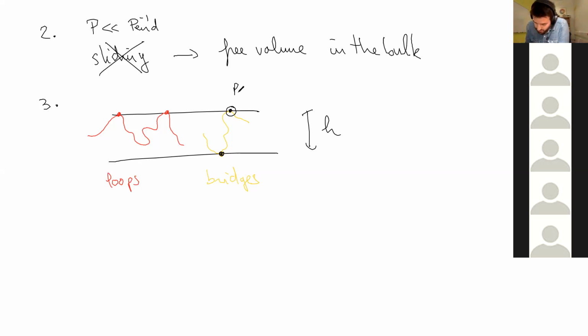So P end, I mean, it's a suppressed penalty. It goes to 1. There is no more free volume constraint for the leader. Then the sliding mechanism becomes very competitive because you only have the motion of the kids behind, and they are much easier than free volume motions because they follow the leader. So that's the main idea by de Gennes. So bridges and loops matter, okay? Sliding matters.